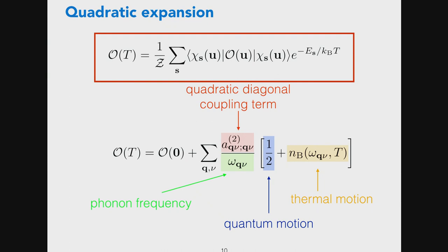The approach I want to describe, or we want to use actually, is based on finite differences. Expressions like these are also amenable to linear response methods, which have many advantages, such as the ability to use a single primitive cell to do the calculations. But finite difference methods also have some advantages, and these will prove essential for some of the applications I'll show. In particular, you can use them very easily with any sort of electronic structure method that you want, because you calculate the coupling by explicitly distorting the atoms in your system, and then you can use GW, hybrids, whatever you want in that context.